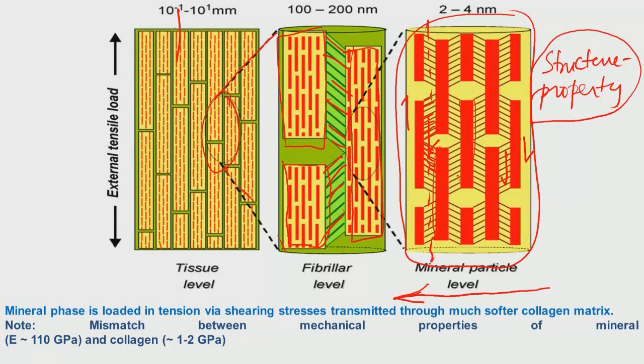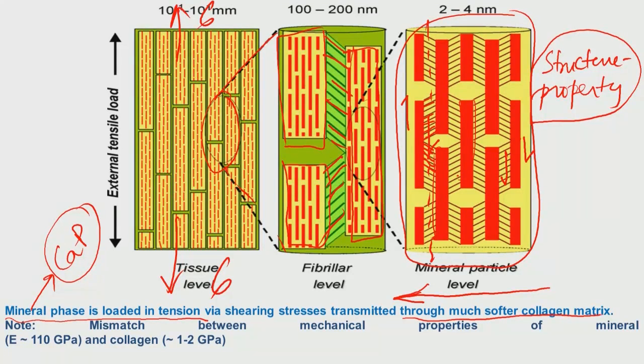So now when you apply that external stress sigma, what will happen? The shear stress will be generated along the bundle circumference, and that is what is mentioned in the next slides. But before that, let me also underline some of the important concepts. You have a mineral phase, that is calcium phosphate or hydroxyapatite in this bone. When this assembly of collagen as well as hydroxyapatite nanoplatelets is placed under tension, what will happen? The calcium phosphate phase will be placed under tension via shearing stresses, and that will be transmitted through the elastically softer collagen matrix.